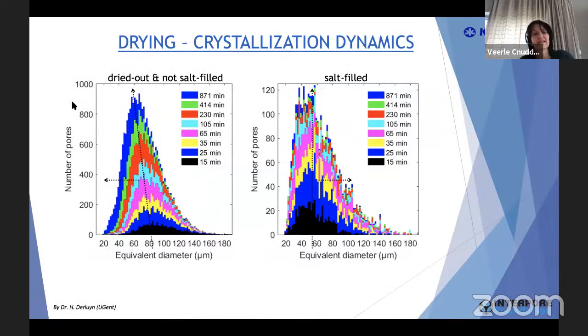So you can then start to follow, in which pores with which equivalent diameter you have drying out and no salt being filled, and how this is progressing as a function of time. So here we see from the bigger pores to the smaller pores, while we can also see that the salt is being filled typically in the smaller pores and going slowly to the bigger ones.